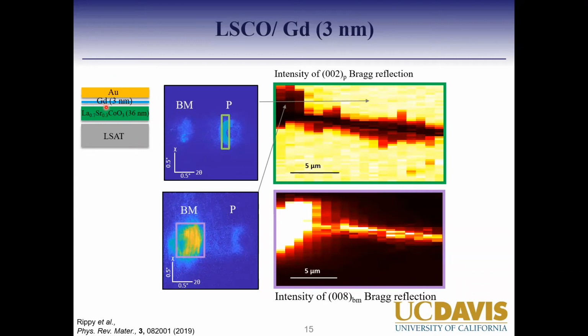But in this case, what we are not sure about is, as gadolinium gets oxidized, because that's what's happening, is there a distribution between gadolinium and gadolinium oxide across the gadolinium layer. That we are not sure of yet. If I just grew gadolinium without the LSCO, we know that layer is homogeneous and smooth. But when we grow on top of LSCO, it converts into gadolinium oxide, and that distribution between gadolinium and gadolinium oxide, I cannot comment on yet.